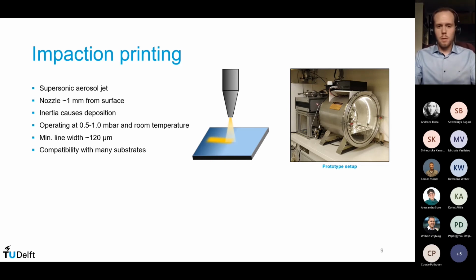So the working principle is that you have a vacuum chamber with the nozzle, and the nozzle is connected to your spark ablation generator. And the aerosol is accelerated through this nozzle because of that pressure difference. Now this jet can go supersonic speeds, and if you place it close enough to a substrate, so that's less than, I would say, a few millimeters, the inertia of the nanoparticles will cause them to land on the surface and stay there. So you're essentially spraying the aerosol on a substrate, and if you move the nozzle very close, you can even have, to a limited extent, some sintering. So the particles will be electrically connected.